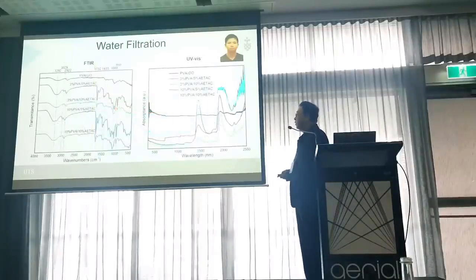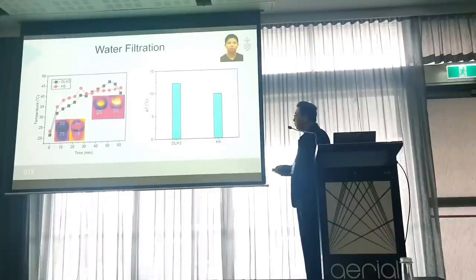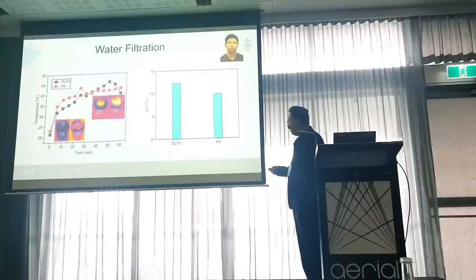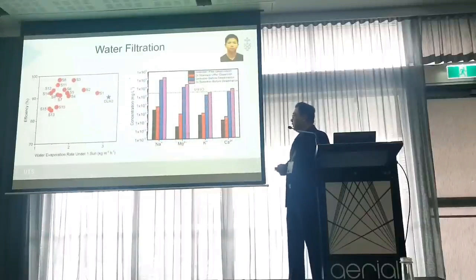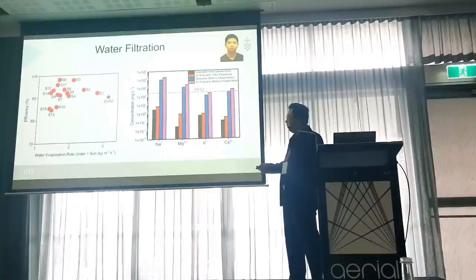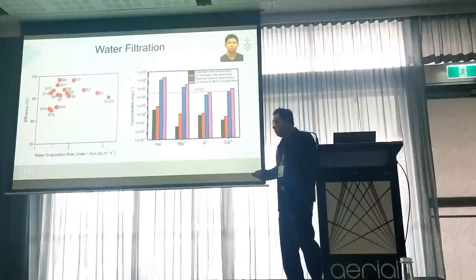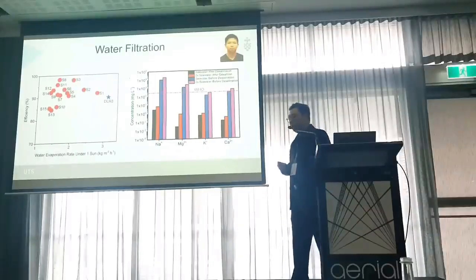So we characterized them with FTIR and UV-Vis, and first we demonstrate that the dual-layer configuration can enhance the heat insulation. We tested the temperature of the interface and the bulk water and observed a higher temperature difference compared to the conventional homogeneous hydrogel. We also tested the evaporation performance, 3.1 kilograms per square meter per hour. But more importantly, these hydrogels show a high salt rejection ability.